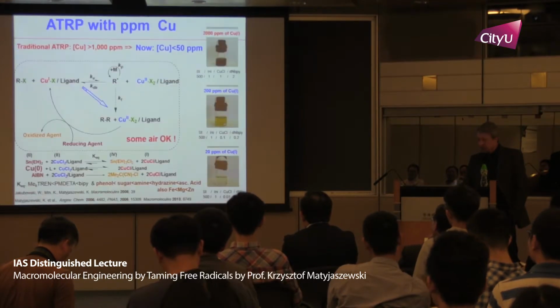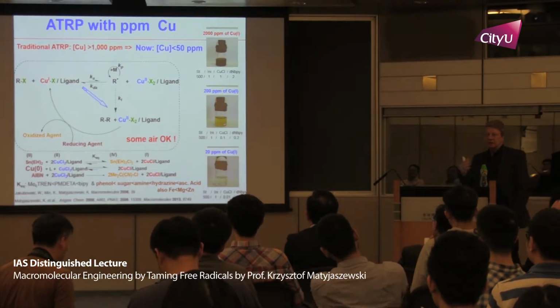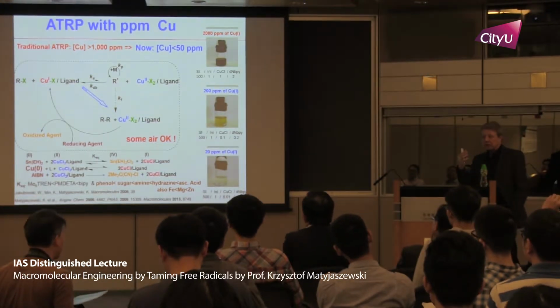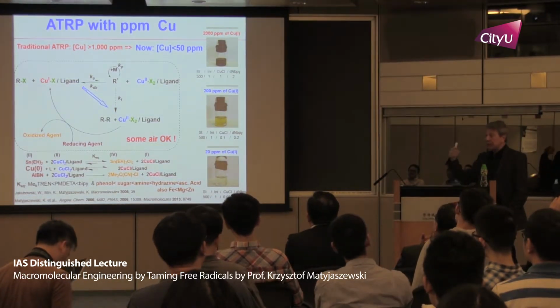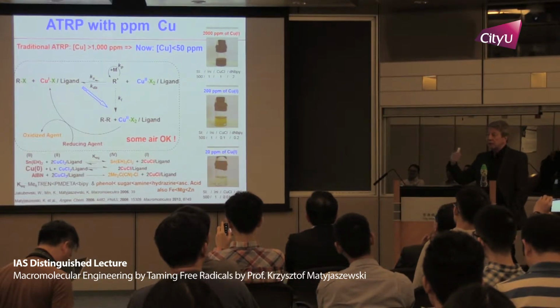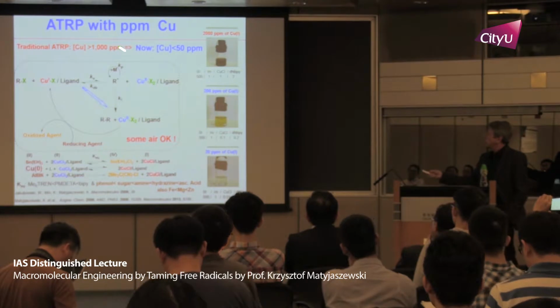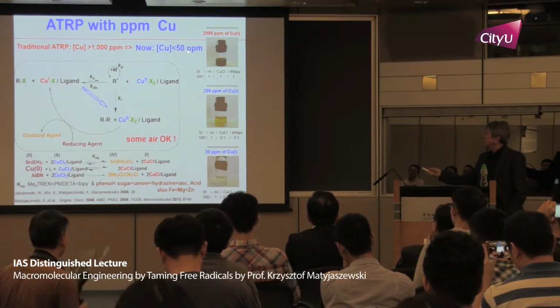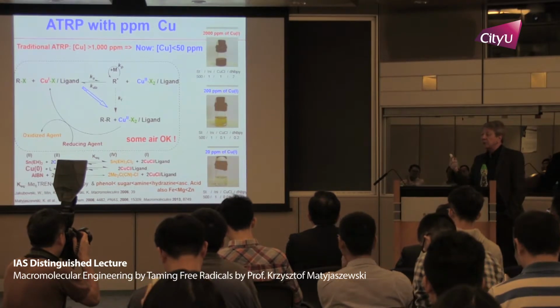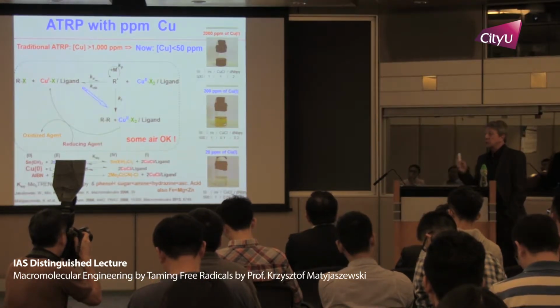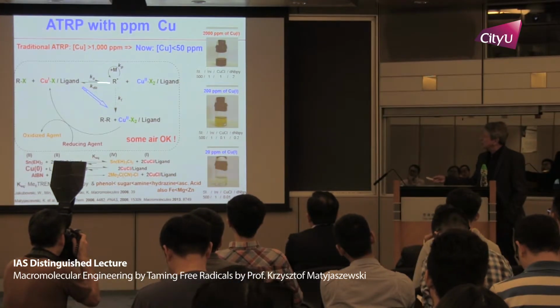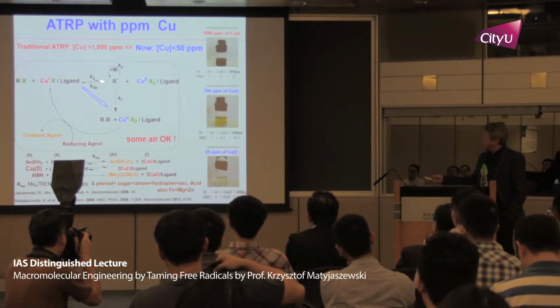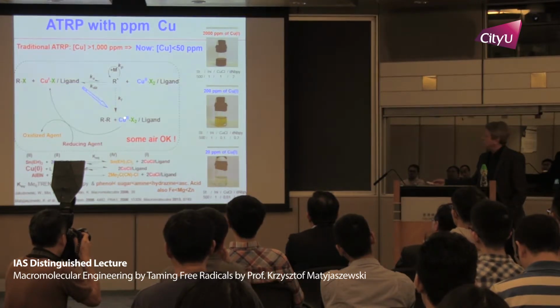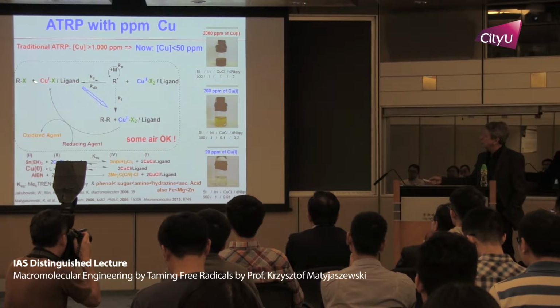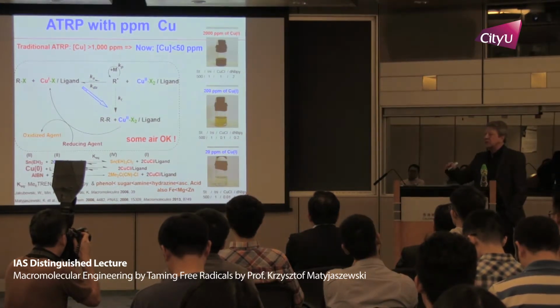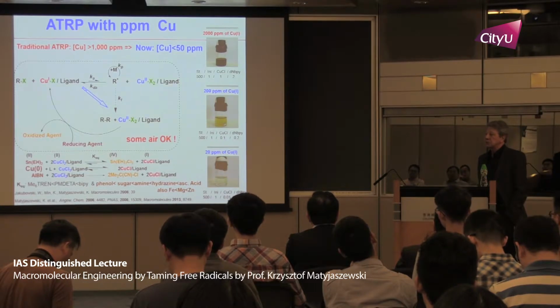So I told you that we develop more active catalysts. This is really one of the areas and targets of our research. So instead of, like organic chemists, using 5 mol%, we started to use 1 mol%, 0.1 mol%, and eventually 50 ppm, sometimes 20 ppm, sometimes even 1 part per million. So these systems work. If you have very active systems, they can exchange very fast. But I mentioned to you that radicals always terminate. If they terminate, you convert irreversibly activator to deactivator, and the reaction stops at maybe 5% conversion.